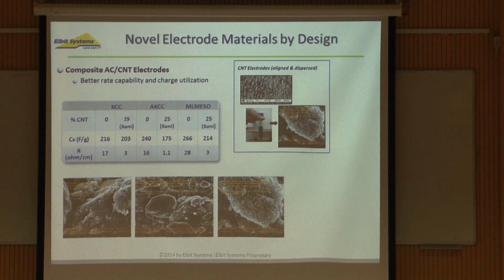We found out that especially for the design of our own electrodes, when you take CNTs with a specific area of, let's say, 400, 500, up to maybe 600 square meter per gram, and compare it with low-cost activated carbon with a specific surface area of above 1,000 square meter per gram, then, of course, in terms of the surface area, they cannot compete. The surface area of the activated carbon is good enough, and if you have an optimized ion size of your electrolyte that gets to each and every one of those pores, then you will achieve the optimal capacity.